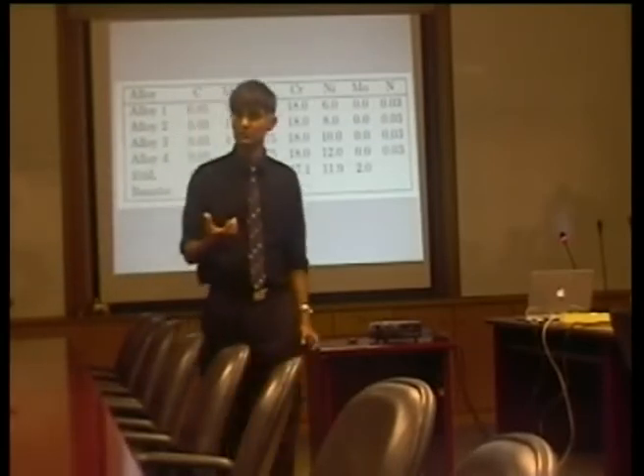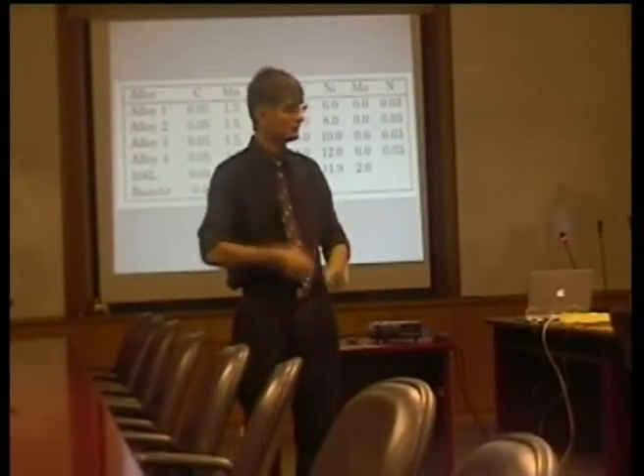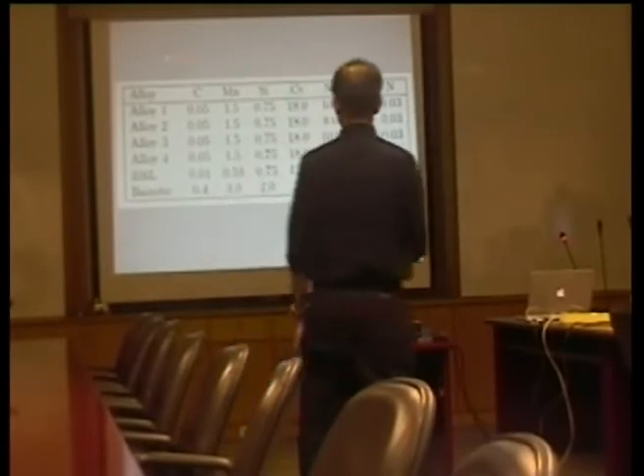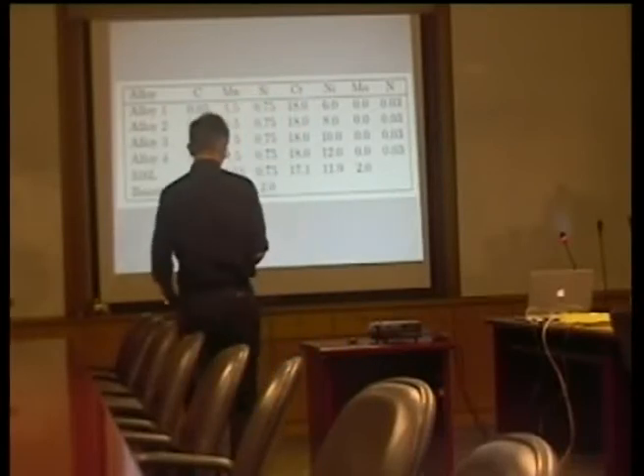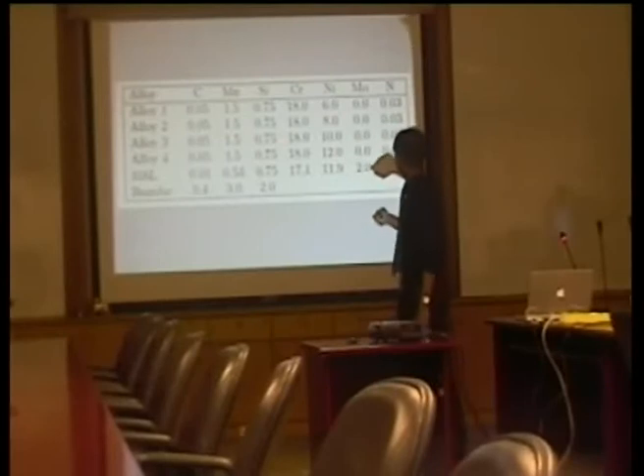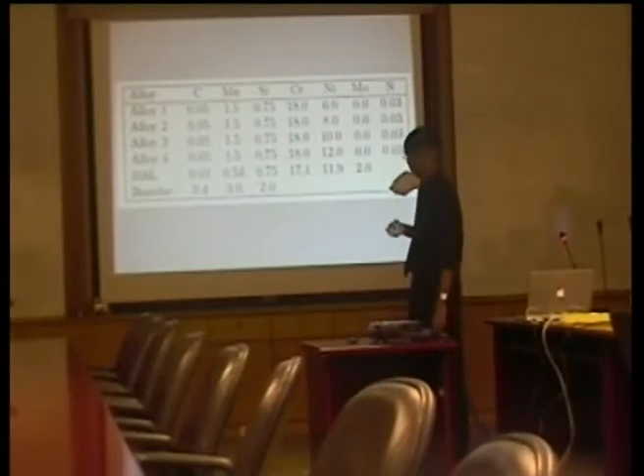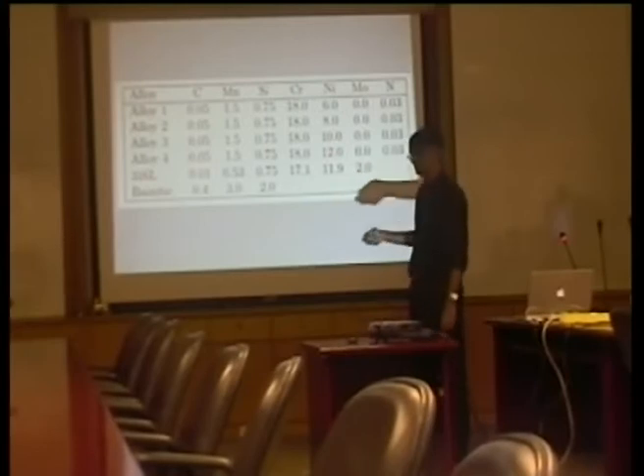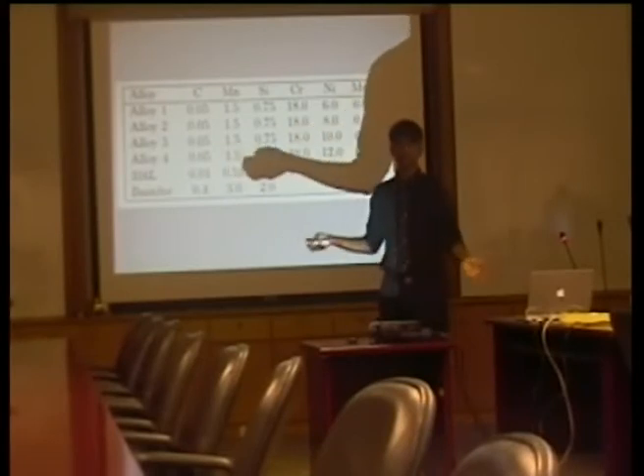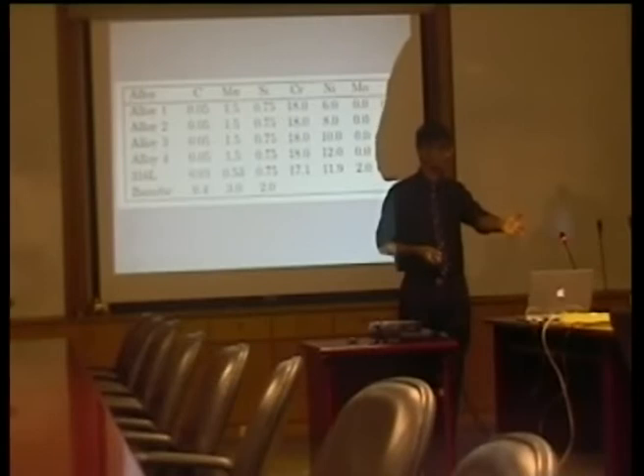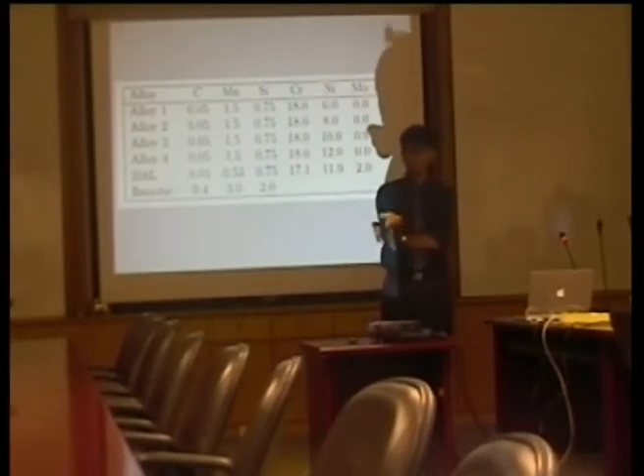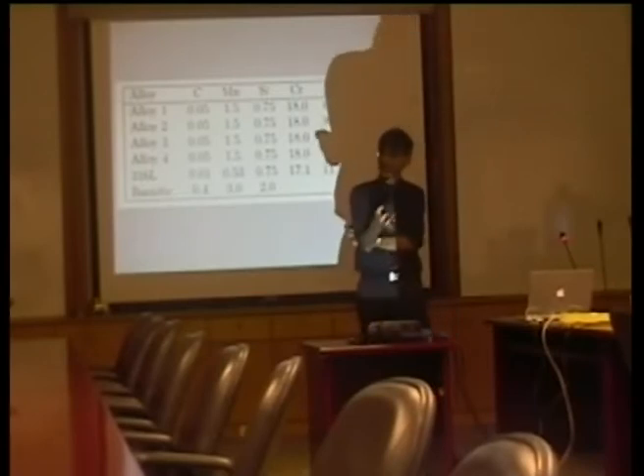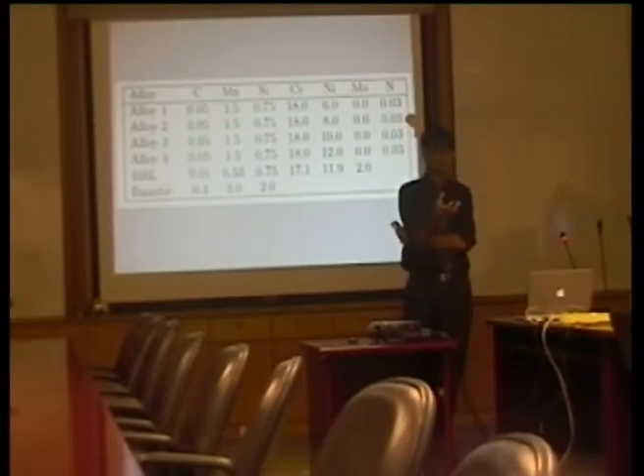And we have tested this theory because in this theory we can also vary the chemical composition of the steel, because that will alter the driving force for transformation. So supposing that I make hypothetical alloys, alloys 1, 2, 3 and 4. They're all based around 316L but with different nickel concentrations, starting from 6, 8, 10, 12. And this alloy 4 is almost exactly like 316L. But what I want to discover is not only the strain at which mechanical stabilization happens, but what if I alter the nickel concentration? Will the mechanical stabilization happen at a later strain or an earlier strain? Because we have that delta G, which is the driving force for transformation from austenite to martensite, that depends on the composition. So in this theory, we also can change the alloy completely and predict a new strain for mechanical stabilization.